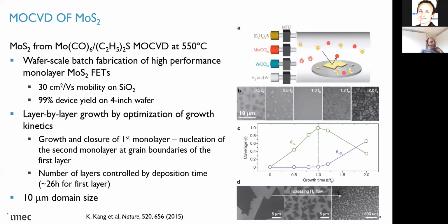There is only one drawback in this paper. It's that the growth time was very, very long and not completely compatible with high volume manufacturing processes. And the other thing is that you have non-oriented crystals, because you're growing on silicon oxide, so nothing is organizing this. And therefore, it has some limitations towards really boosting the performance to higher levels.